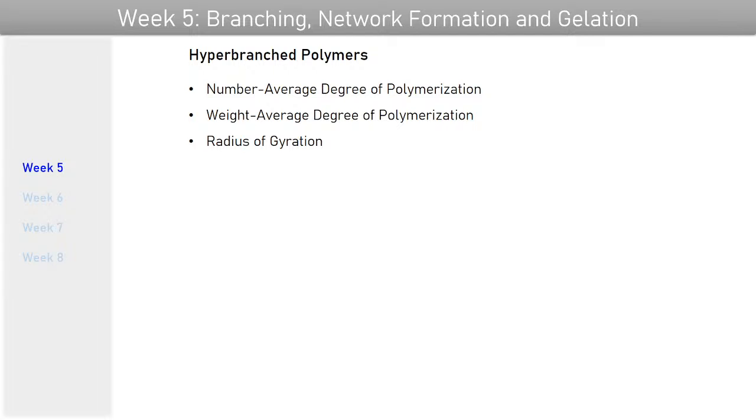These were the specific cases that we discussed under branched polymers, and then we moved on to network polymers, where we studied the concept of gelation, briefly discussed the Flory-Stockmayer theory of gelation, and towards the end of this week we also talked about the Flory-Rehner theory of swelling. When a solvent is added to a network polymer, instead of the polymer getting dissolved in the solvent, you actually have swelling of the polymer. That was discussed in the Flory-Rehner theory and the corresponding equation which describes this swelling behavior, towards the end of week 5.